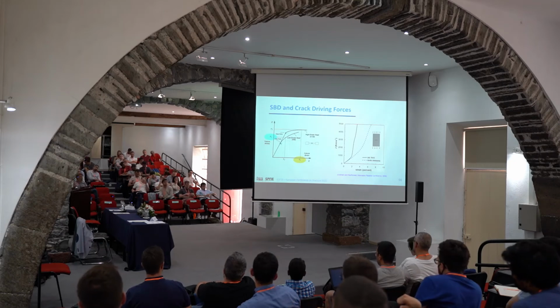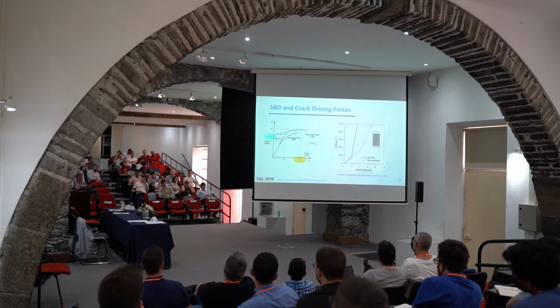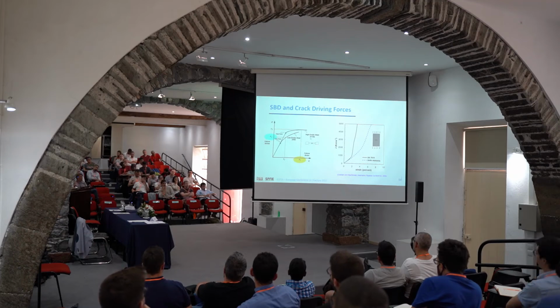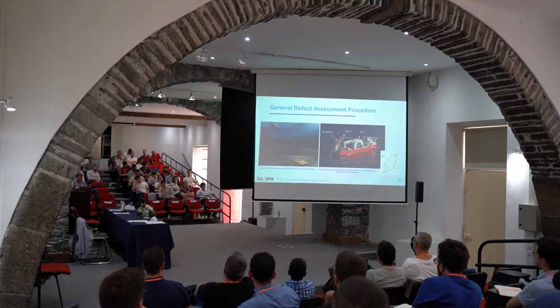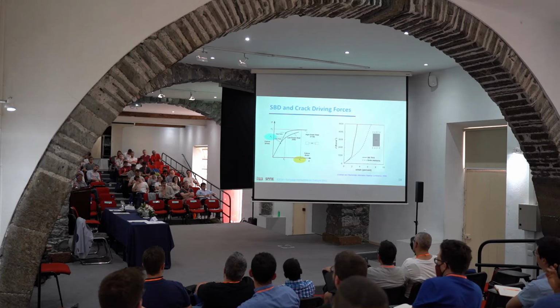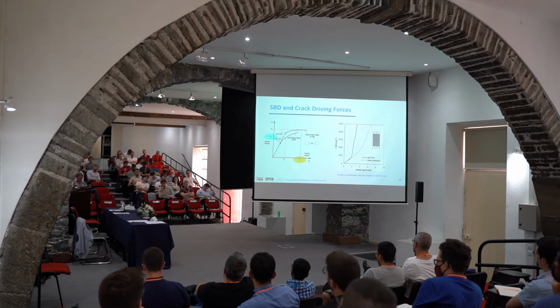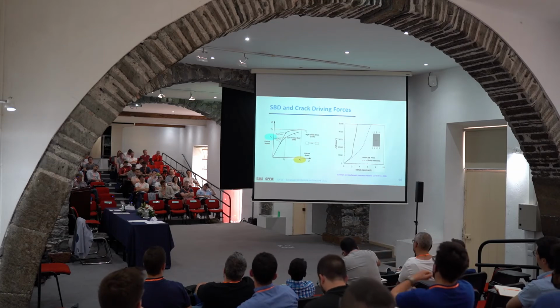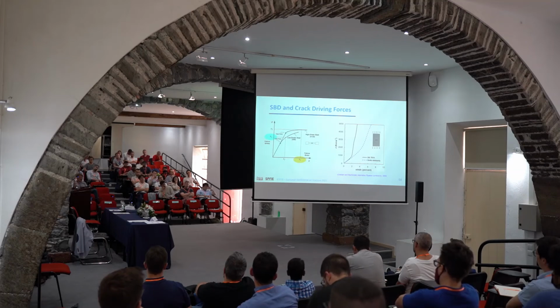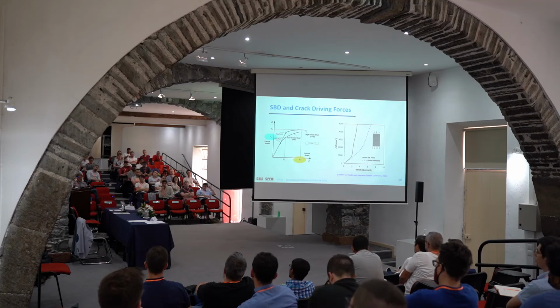You see here it's a high hardening material, and this is the new generation of high strength steels, X100. So X60 is a yield stress of 60 KSI. Again, these are American units, kilopounds per square inch, which is roughly 400 megapascal. And X100 is 100 KSI. It's more or less 680, 700 megapascal yield stress, so it's much higher.